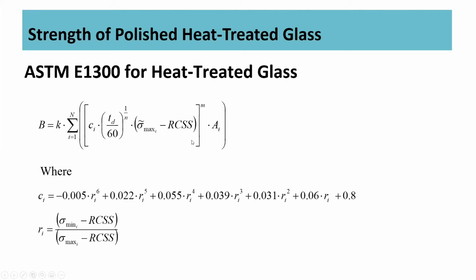Now, when we use this method for design purposes, the standard requires us to use the minimum RCSS values that are specified in C1048. So that'd be 3,500 PSI for heat strengthened glass, and that'd be 10,000 PSI for fully tempered glass. But in our experience, we found that often glass is not at the minimums. There's something above that. But we do know that, for design purposes, you never know what you're going to get on the job site. So it's best to design with the minimums.